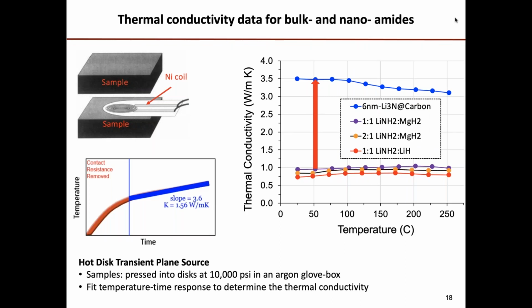Now, we're also measuring the thermal conductivity, and the way we do that is we take powders of these hydrides and we press them into discs at about 10,000 psi in a glove box, and then we sandwich it around a little nickel coil, and when you heat that, you get a change in the heat release of the material, and you measure that, and that slope is related to the thermal conductivity. The data that I show here on the right illustrates just this dramatic effect of nanoscaling. You can see that all of these three bulk materials are around 0.7 or so to about 1, and it's pretty stable with temperature. But if you nanoscale it, the thermal conductivity shoots up by a factor of at least 3.5. So this is really a dramatic effect.